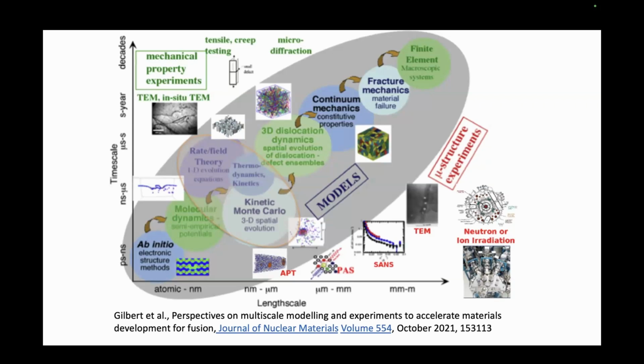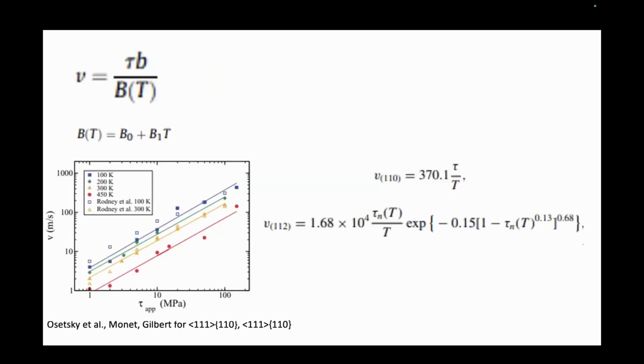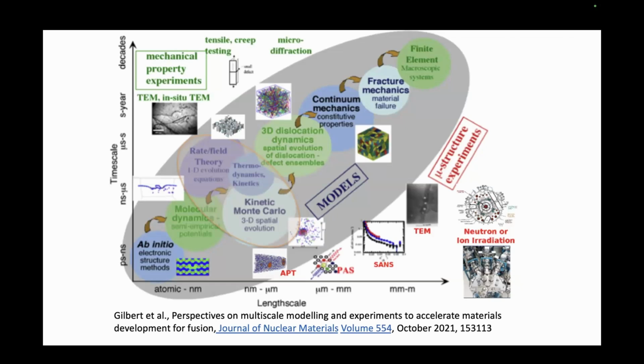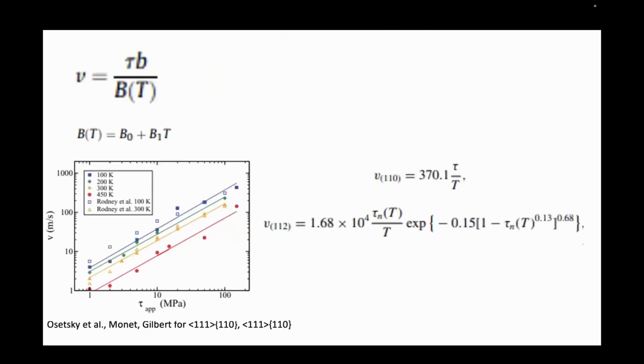The mobility law for hydrogen embrittlement: we really don't know whether hydrogen impedes the dislocation, slowing down its speed, or whether it can shield the stress field of the dislocation and increase its mobility. Then we need the mobility law. Mobility laws can be derived from molecular dynamics simulations, at the atomistic scale. So we performed several MD simulations just to capture the effect of hydrogen on the mobility law of edge dislocation.